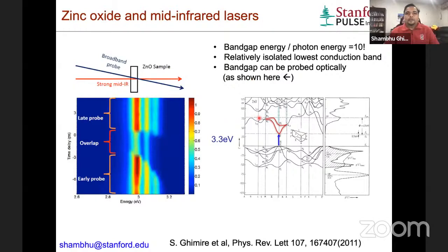So we got that. That was a good start. And there are a couple of other reasons why we tried zinc oxide. One is that its first conduction band, as shown here, is fairly non-parabolic, and it is more or less separated from everything else, including the higher lying conduction bands. So we wanted to pick a relatively simple system so we could understand what is going on at the microscopic level without too much difficulty. At least that was the idea. And because of the 3.3 eV band gap, we could probe near the band gap using probes that are easily available in laboratories, such as the Ti:Sapphire, and see what happens at the band gap. So these were a couple of reasons why zinc oxide was a suitable candidate.